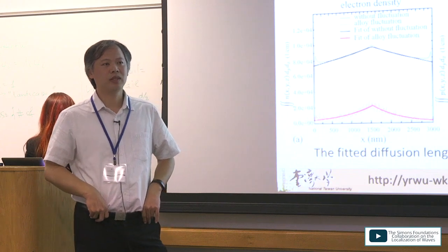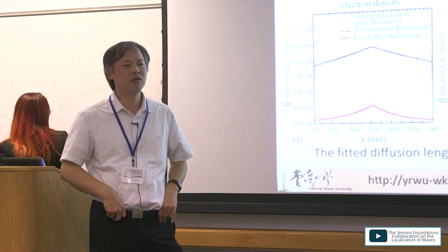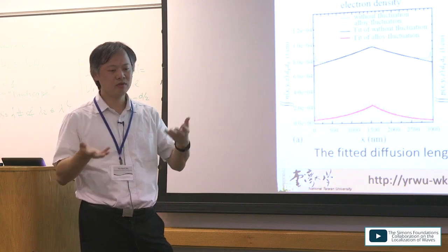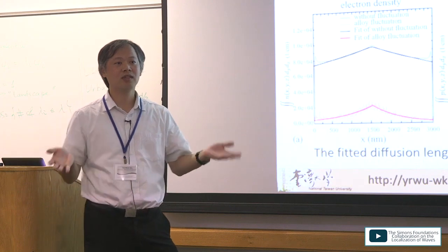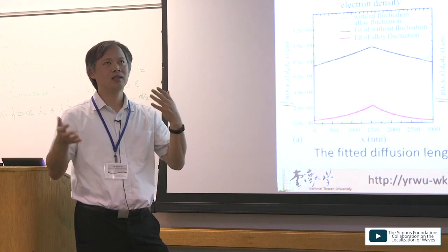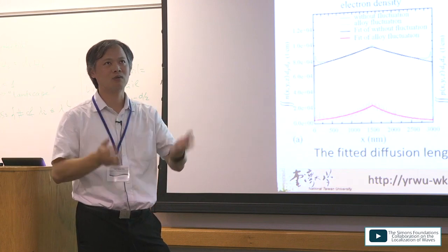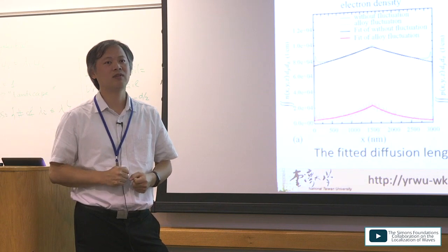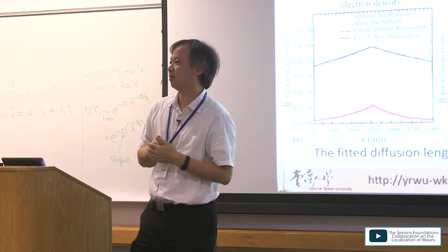But I'm not sure I hear a clear answer. I don't have a clear answer for you, because later on, the new results with better crystal quality have improved dislocations, even if you use a GaN substrate, so you cannot compare to the older one. There are many factors inside. So as long as the dislocation density is as bad as in InGaN, probably InGaN can provide better efficiency. Any other questions? Gotta go quickly now.